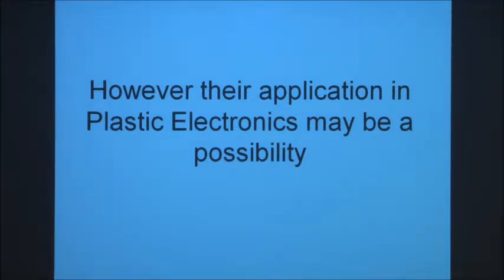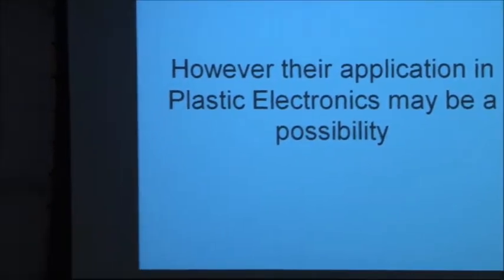But I personally think one of the sort of low-hanging fruit, if you want, for nanotubes is something slightly different, which is actually to look at plastic electronics. Most people, when they speak about plastic electronics, think about organics and other things like that that you can put down in plastic. There's no reason whatsoever why you can't put down carbon nanotubes in plastic. You grow them. Then you make an ink or a solution, and you spray them or you inkjet them, and you can put nanotubes in plastic quite easily. And we tried this a few years ago, and we got pretty rubbish results. But it's quite interesting as time goes on how people improve these things.